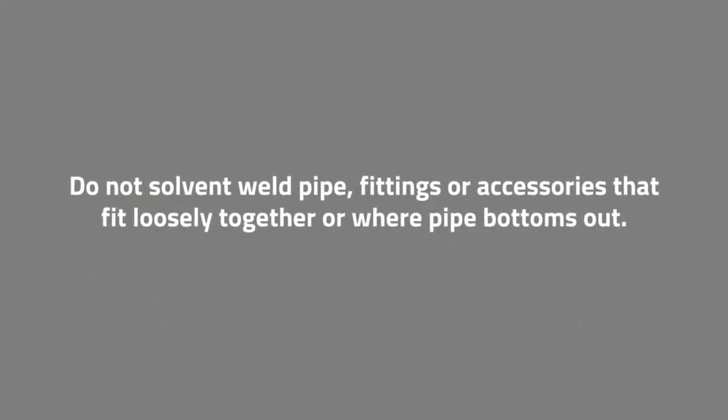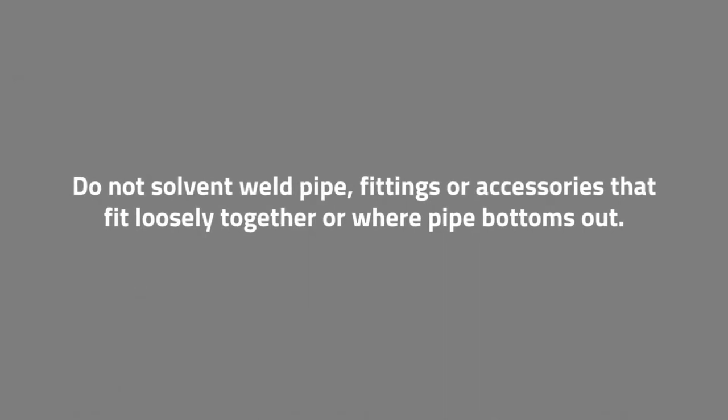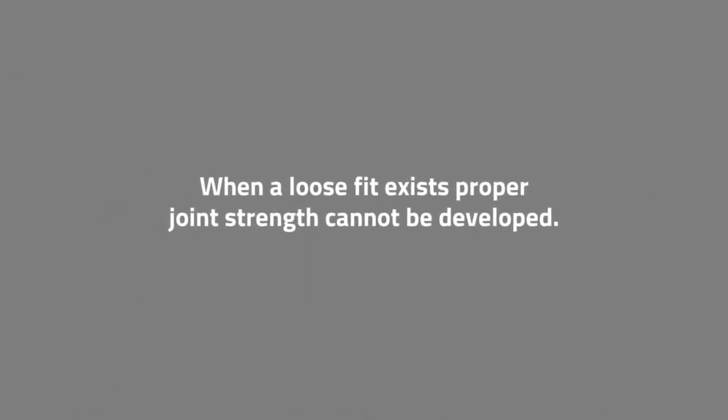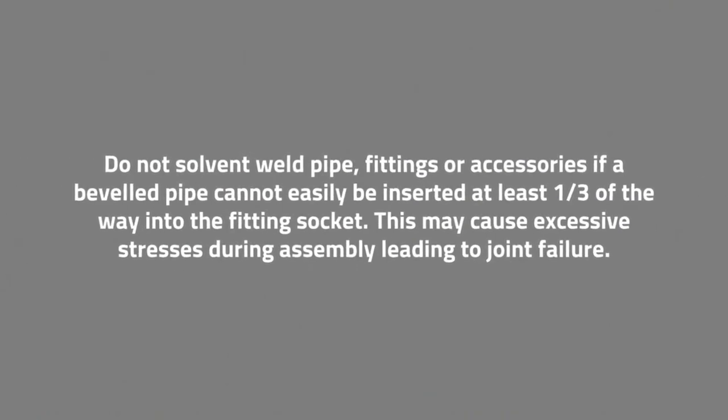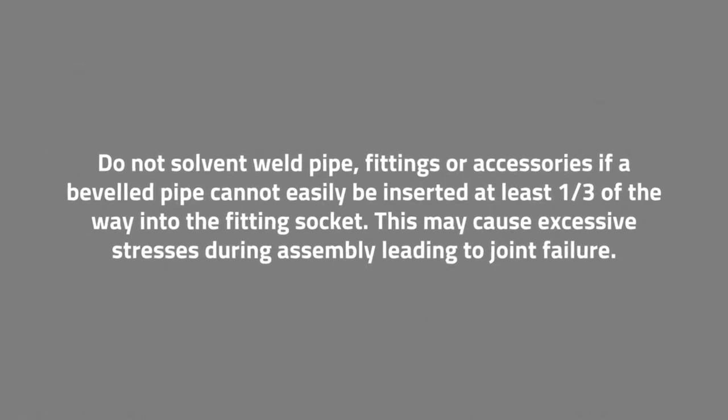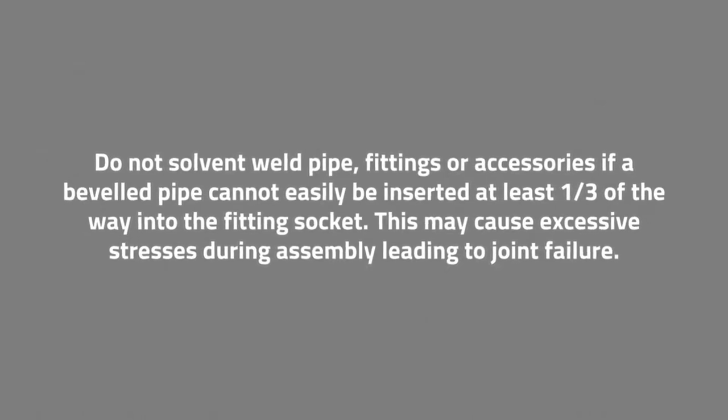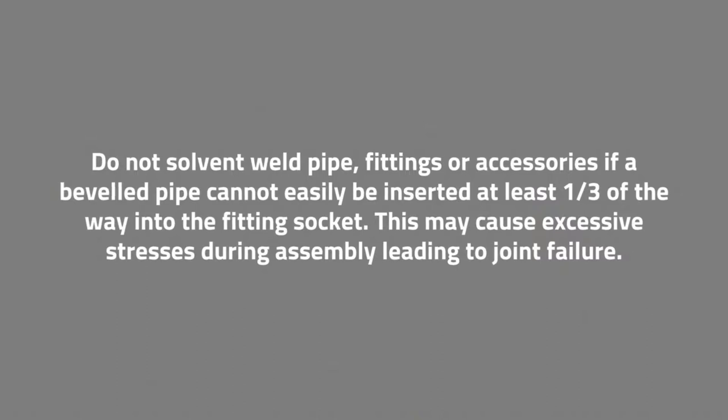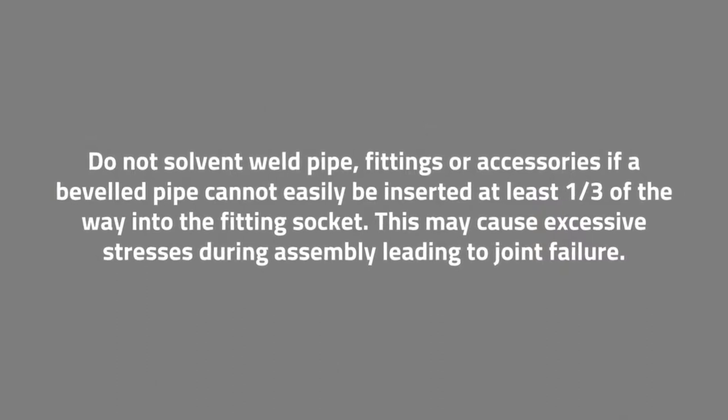Do not solvent weld pipe, fittings, or accessories that fit loosely together or where pipe bottoms out. When a loose fit exists, proper joint strength cannot be developed. Do not solvent weld pipe, fittings, or accessories if a beveled pipe cannot easily be inserted at least one-third of the way into the fitting socket. This may cause excessive stresses during assembly, leading to joint failure.